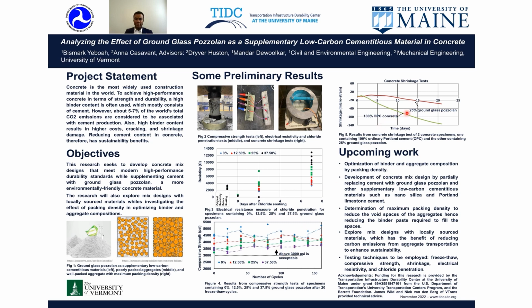Also, figure 5 shows the concrete shrinkage test of two concrete specimens, one containing 100% ordinary Portland cement and the other containing 25% ground glass pozzolan. So the specimen containing 25% ground glass pozzolan has relatively lower shrinkage than the specimen containing 100% ordinary Portland cement, as can be seen here compared to this.